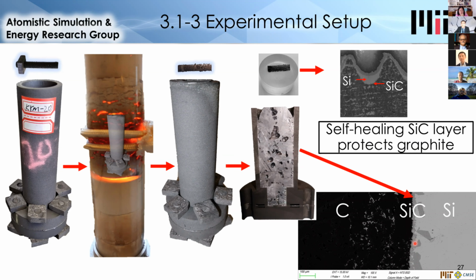carbon. And so this figure in the bottom right shows that we have graphite, and then a thin layer of silicon carbide, you can see is about 20 microns thick, and then silicon. And this is exactly what we want to see. We know this happens at lower temperatures from previous reporting, but this was at up to 2300 degrees Celsius. The silicon carbide layer remained attached and protected the carbon from further reaction with the silicon.